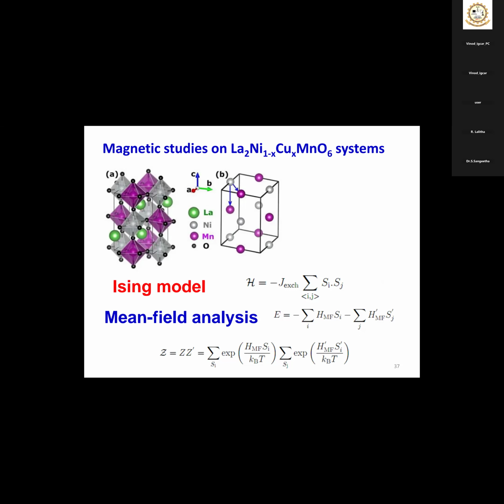The simple Ising model is like this: nearest neighbor exchange interaction. You can see the left figure A is the primitive unit cell. Figure B is where we have removed all the non-magnetic ions. Only magnetic nickel and manganese are shown, with non-magnetic lanthanum and oxygen removed. The nearest neighbor interactions I have marked with arrows. You can see how the nearest neighbors are there, and these nearest neighbors will interact.